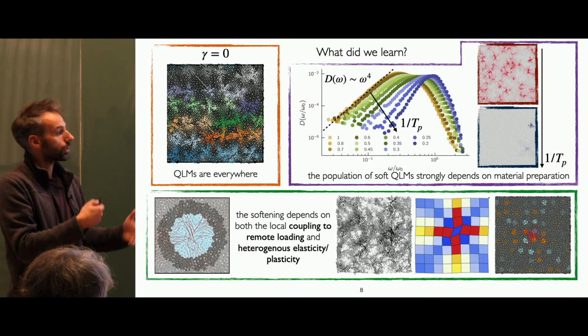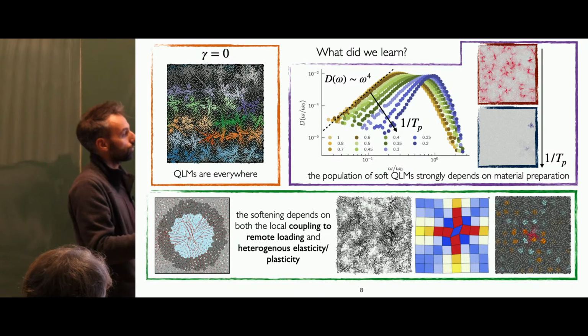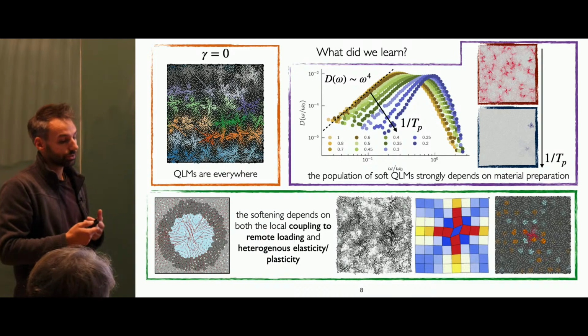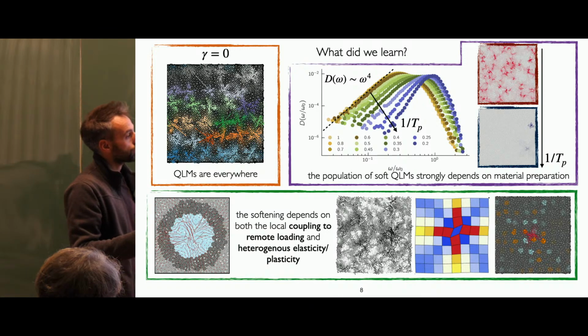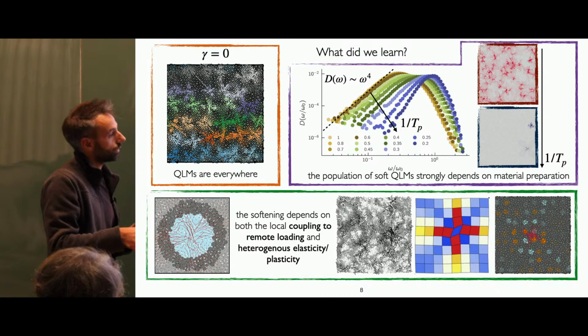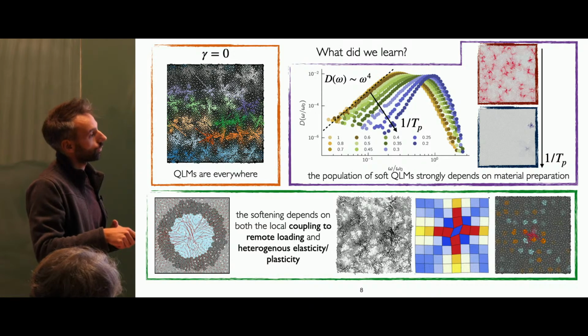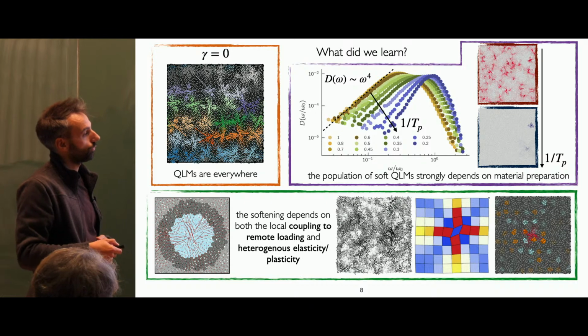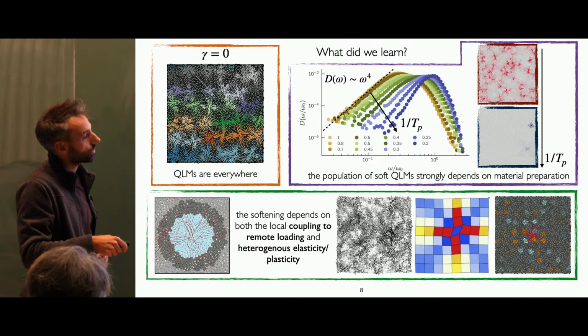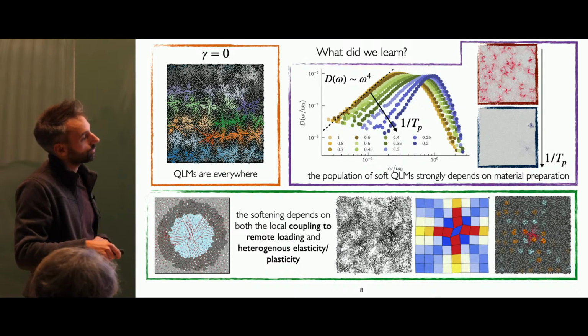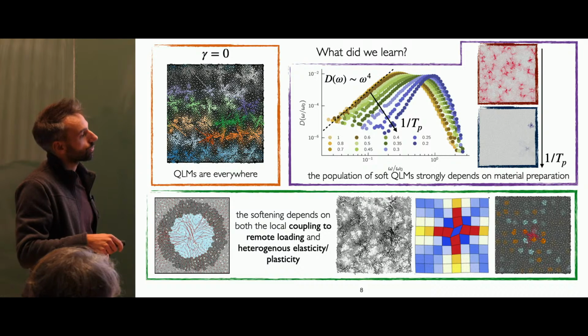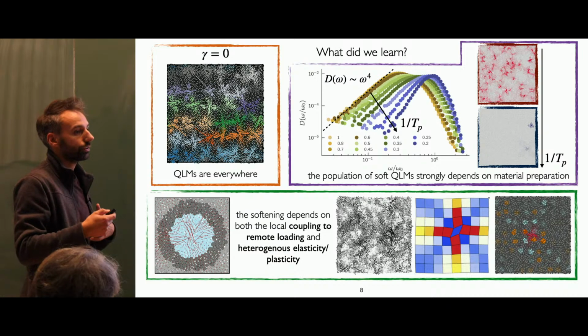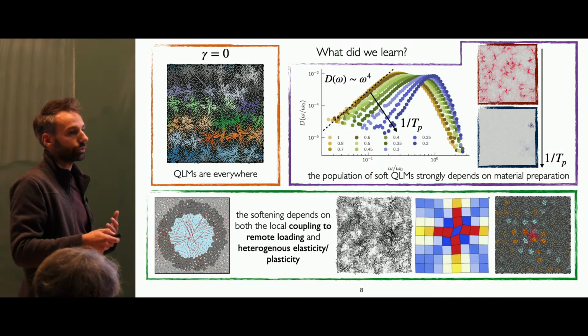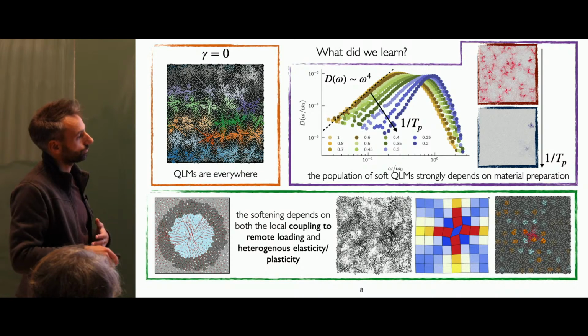When you start to see dissipation and a shear transformation, we also learn that there will be some stress release across the system, and those will also be long range and follow the Green's function of a glass. What it means in practice is that when you have a shear transformation zone, all the modes and the defects around will be less affected if they are far away, but there will also be a symmetry. Some modes will stiffen and some modes will soften in a particular fashion.